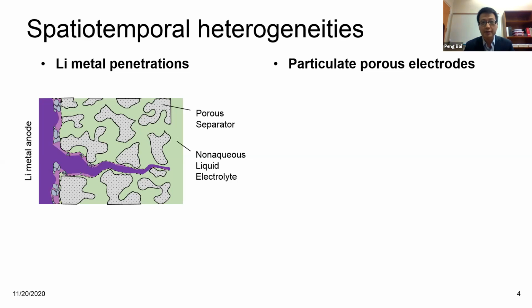there are some very interesting properties. But if you think about the penetration, there are really two steps. So for example, here, what I show is that we already have this lithium deposition, the purple one. But then when you have a real battery, you have a porous separator. It's inert. It has pores. The pores are wetted by the electrolyte. Then you have this kind of heterogeneous interface. But this interface will already give you some structural heterogeneity. And what happens is that